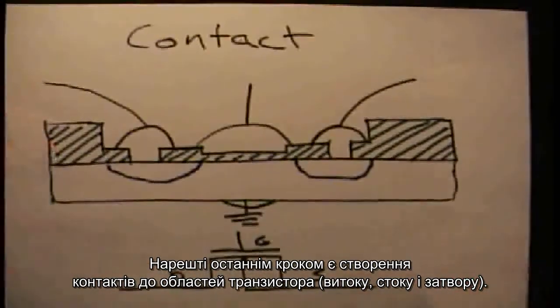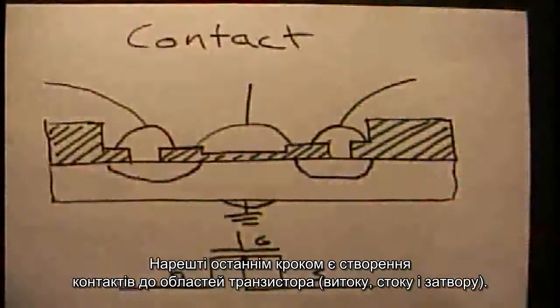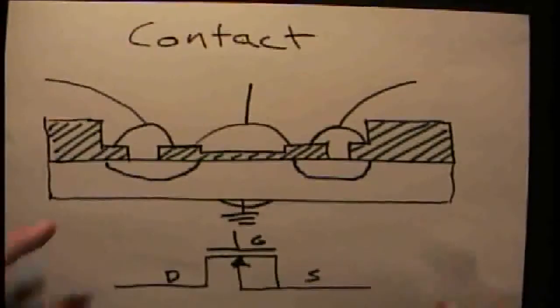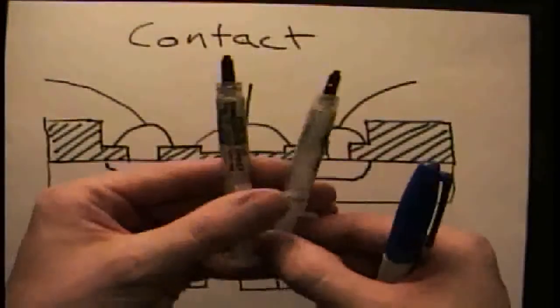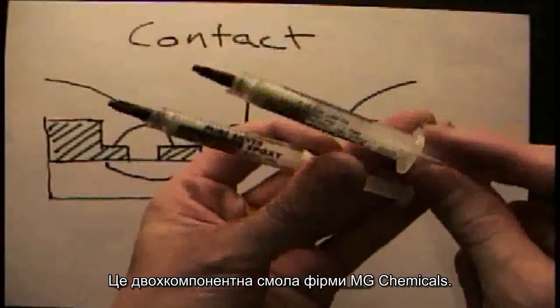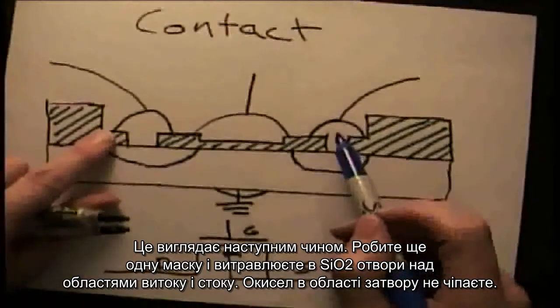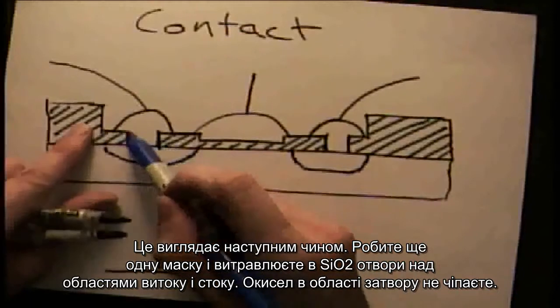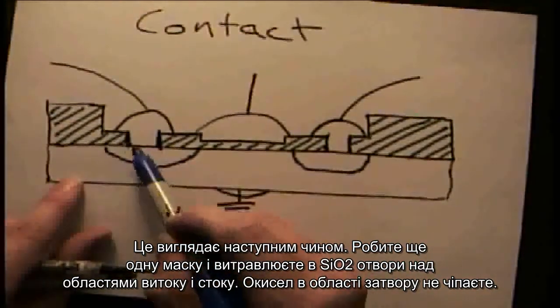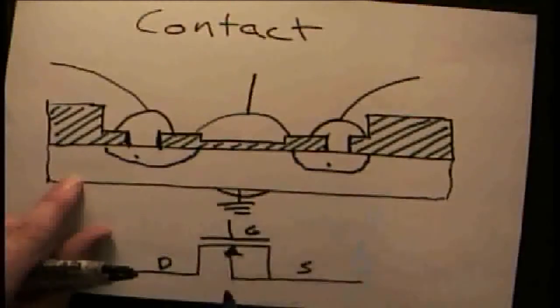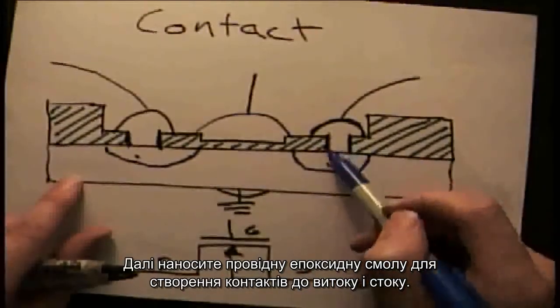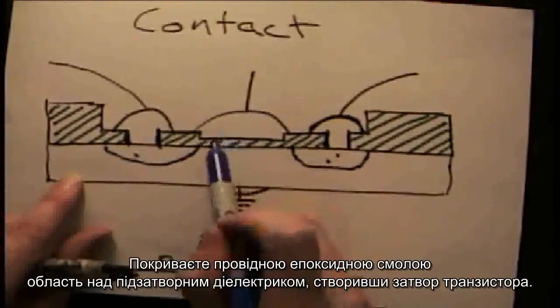And now for the last step is the contacts, to make contact to the various parts of the transistor. What I use is conductive epoxy. It's a two-part epoxy. This particular type is from MG Chemicals. And your side view will look like this. You'll make another mask. You'll cut through the oxide that's grown. You'll make access points down to the source and the drain, and you'll leave the gate oxide alone. And then you'll put blobs of epoxy to make contact to these areas. And then you'll cover the gate region with epoxy.